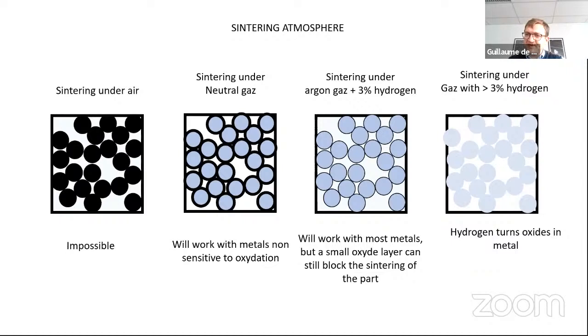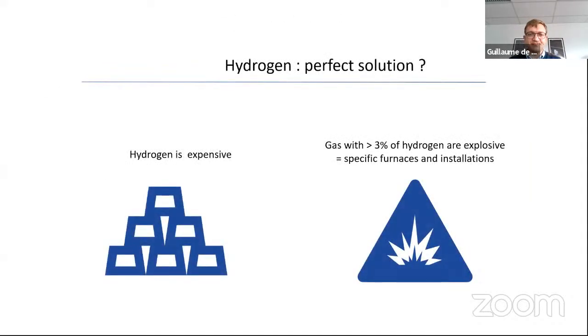Some metals are a bit sensitive to oxidation, and we will prefer to sinter them with a bit of hydrogen, but in some cases we may even need pure hydrogen, and that's really the more problematic thing. Why is it problematic in that case? It's for, again, a quite simple reason. If you get to more than 3% of hydrogen, the gas mix is explosive. Less than 3%, it's considered non-explosive, so there's really no specific hazard.